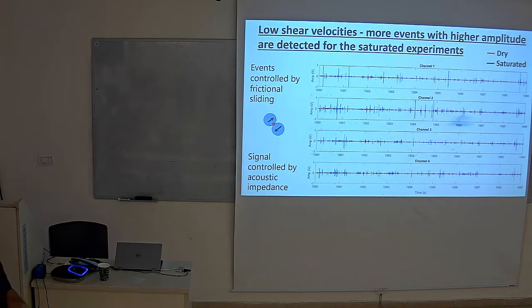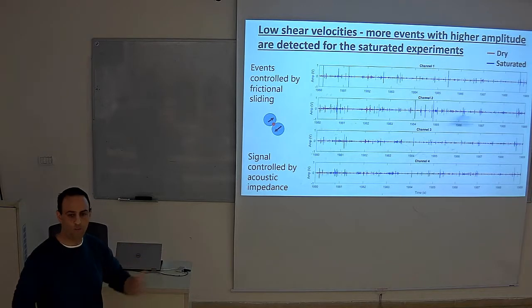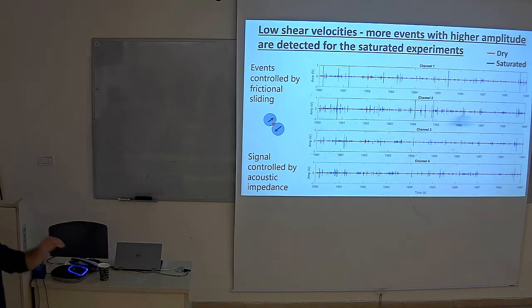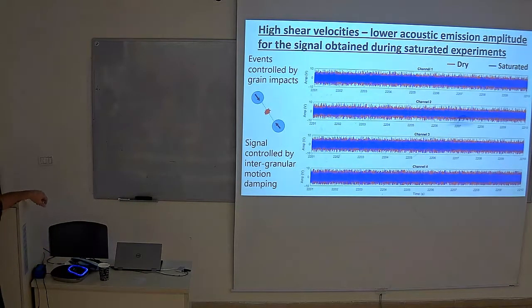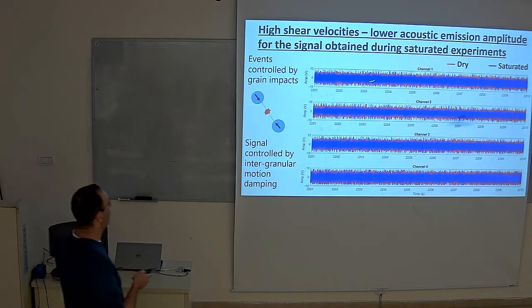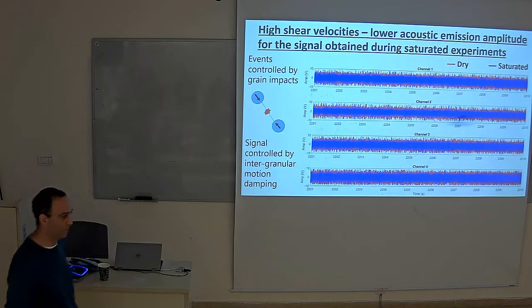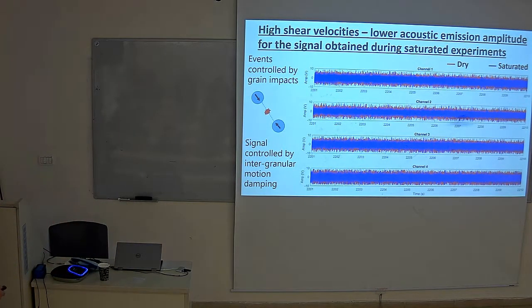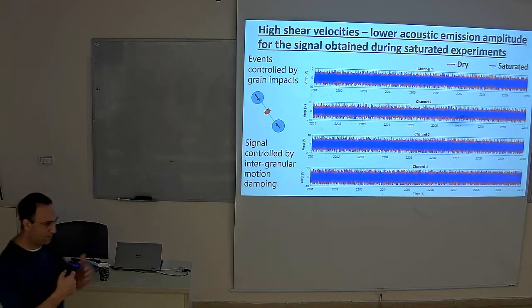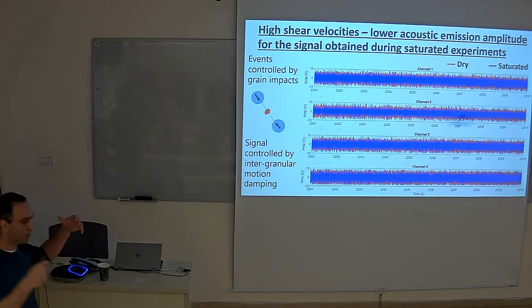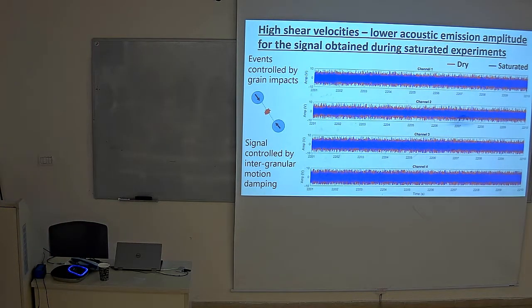However, if that's true, we need to look at all velocities and see the same phenomenon at all the velocities. That is, for dry, we would always have less acoustic energy. But when we look at the high velocity experiment, we see exactly the opposite. We see that the power, the amplitude of the dry experiments, is somehow higher. And what we think is that the grain impacts are actually damped by the fluid, and therefore the collision is less energetic, and there we have less acoustic energy released.